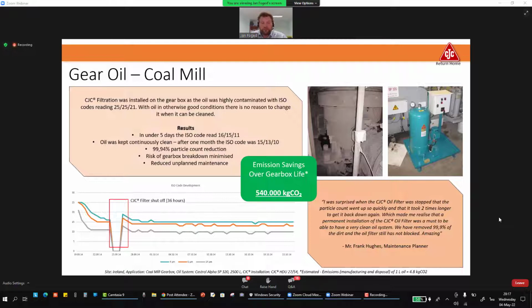But what we also realized here was when the offline filter was turned off for about a day and a half, the contamination came back up very, very quickly to a higher level. It took 3 days to bring it back down to the level it was before the filter was turned off, and it only took a day and a half to get back up. So again, continuous maintenance and continuous filtration will give you the benefits of this extended oil lifetime.